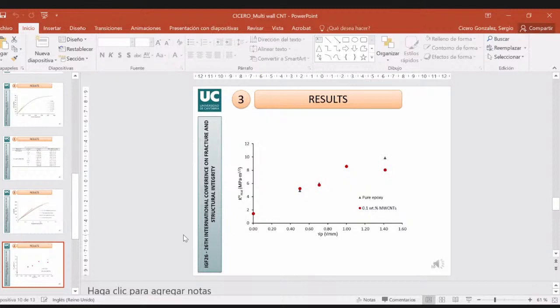And the value of notch root radius in correspondence to which the fracture toughness increased. This slide depends on the nanotube sizes. We didn't use more than one nanotube size, just one, so we didn't analyze that. But what you can see here is that the notch effect is quite big in this method.